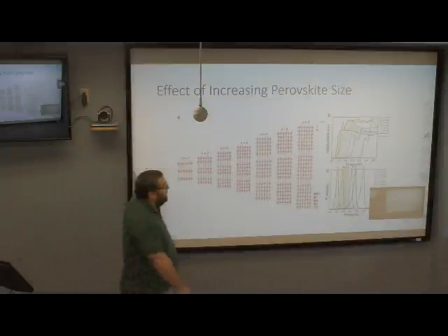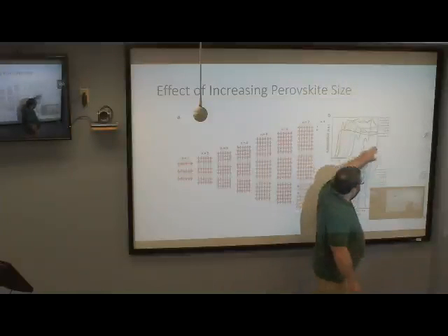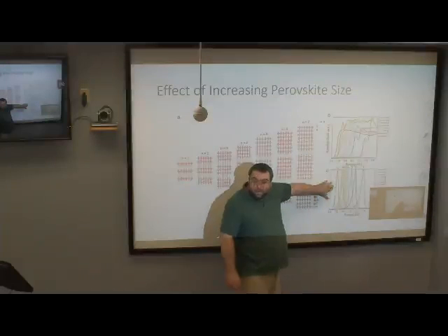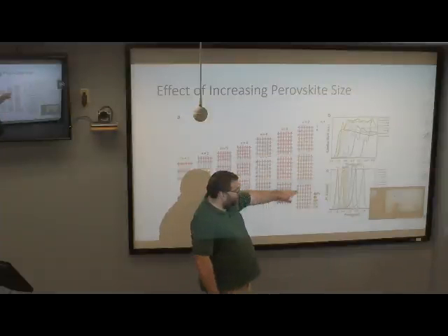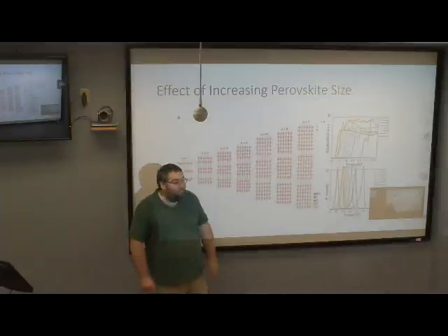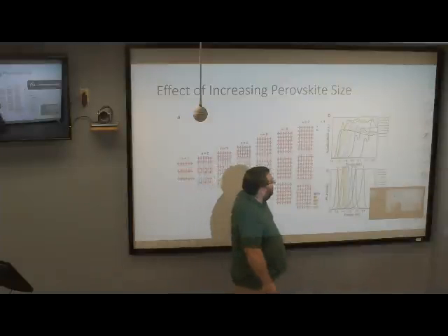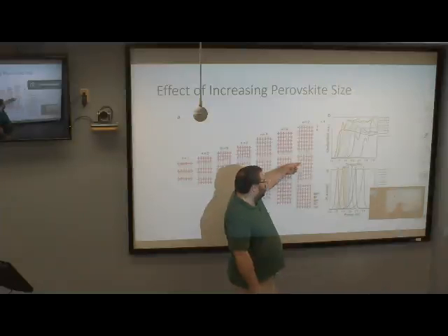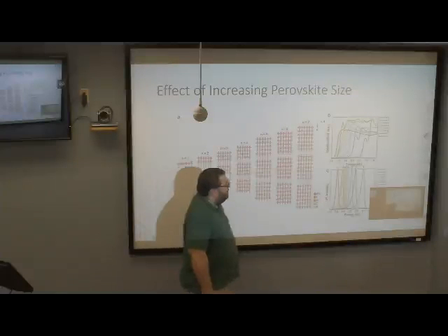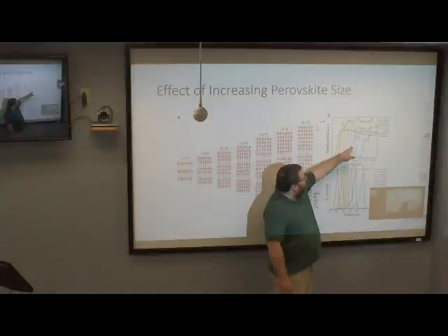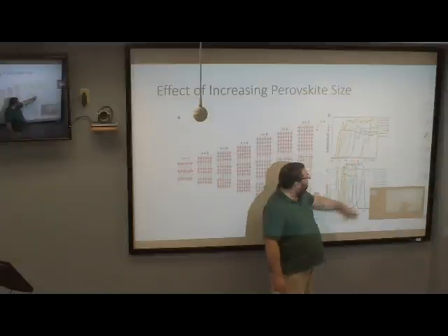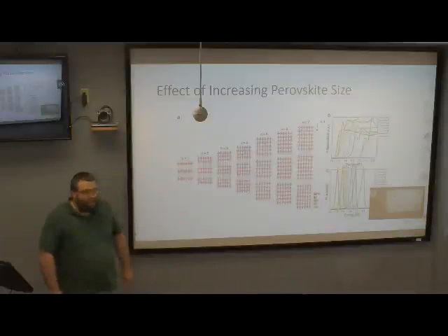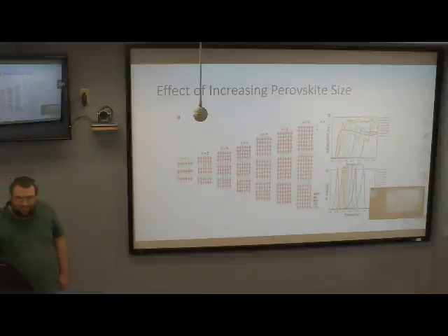So if we look at this, and I need to make this bigger, this first bar here, this red color, is our 3D. The top is absorption, the bottom is photoluminescence. As we go to smaller and smaller perovskite layer size, from 7 down to 1, it blue shifts more and more, eventually getting down to 2.2 eV, which is almost into the UV range.